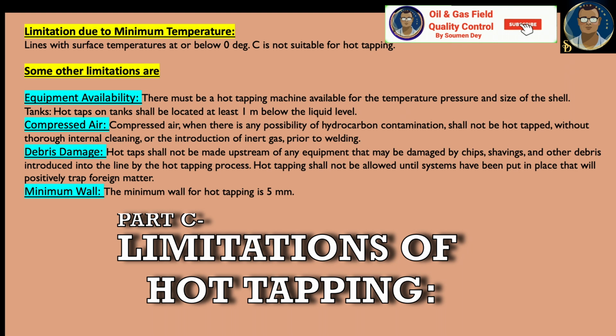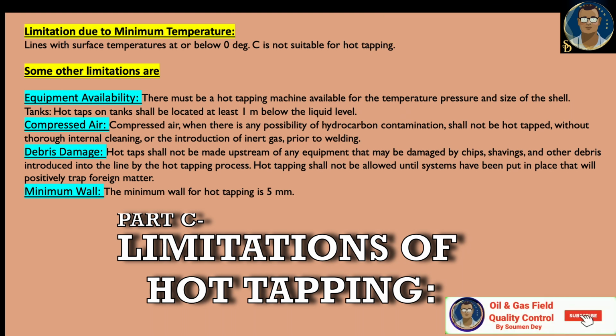Some other limitations we can discuss: equipment availability. There must be a hot tapping machine available for the temperature, pressure and size of the shell. Hot taps on tanks shall be located at least 1 meter below the liquid level. Compressed air: when there is a possibility of hydrocarbon contamination, it shall not be hot tapped without thorough internal cleaning or the introduction of inert gas prior to the welding.